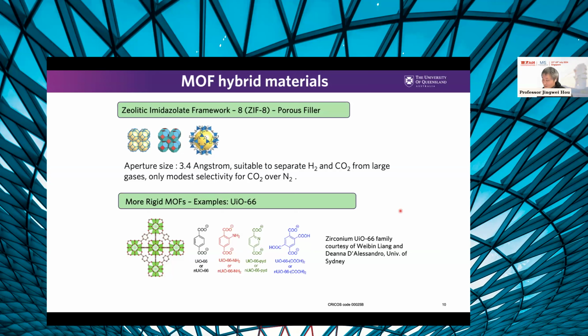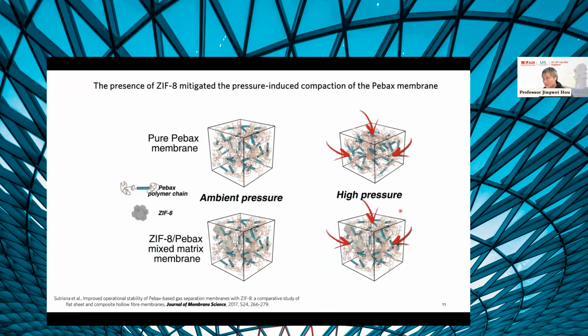So again, I will not go into the details. Everybody should know those two materials very well. So something pretty exciting happened after we put ZIF-8 into the polymer. If we look at the top two lines, this is what happens for the pure polymer membranes. How a membrane can achieve gas separation or water evaporation is because between the polymer chains, there is some free volume. The free volume allows the molecules that we want to separate to go either faster or slower through the membrane. But we have to keep in mind that the membrane is ultra thin, not super sturdy. If we expose the membrane to high pressure, as we did in the flue gas environment, those free volumes will be gradually compacted. In this situation, we will lose the membrane performance. We will lose the permeance, and the membrane is not going to be very selective.